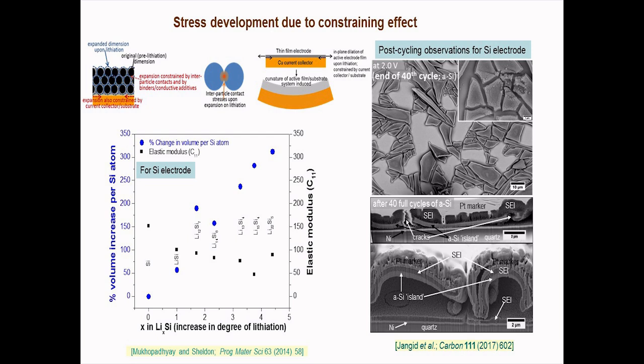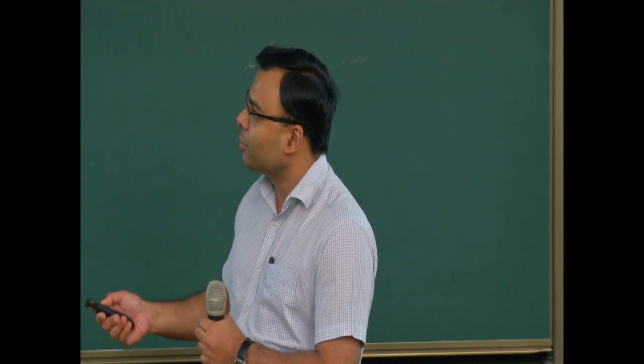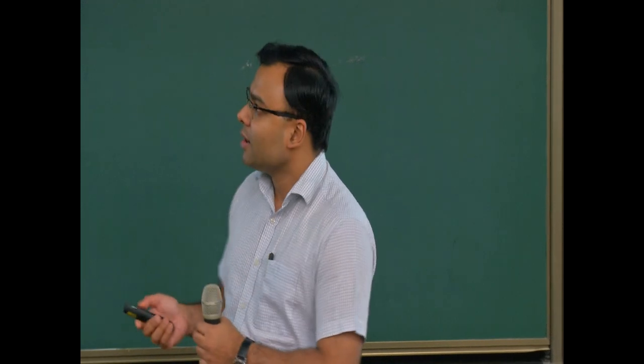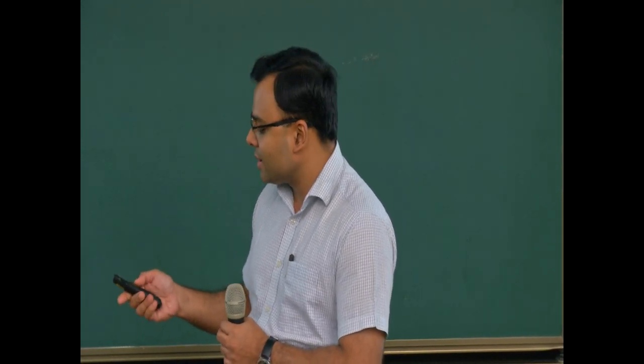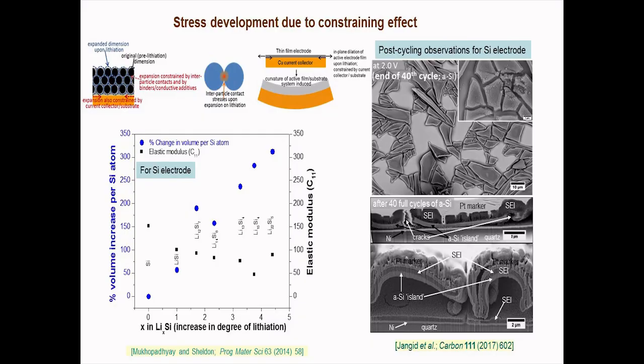Coming to the constraining effect, we can see this is a silicon electrode getting lithiated. Silicon is one of the electrode materials which people are trying their level best to use in lithium ion cells, but still not many lithium ion cells use silicon based electrodes, primarily for this reason, because they undergo expansion by up to 300 volume%, and accordingly they face a lot of constraints. And this is how a silicon electrode appears after cycling for, say, 40 cycles, 40 times lithiation delithiation, from Manoj's work.